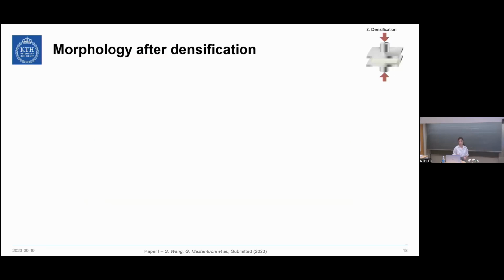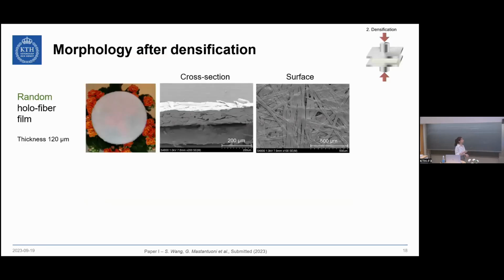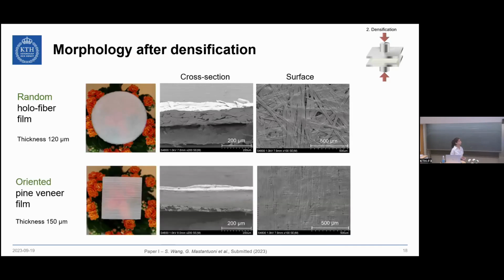What happens after densification? In the first case, with the random in-plane hollow fiber film, we can see random in-plane fibers from the surface, and from the cross-section we can see a lot of gaps inside the structure, which tells us that the packing is not very efficient. Instead, if we press the material that kept its original alignment, even if the material is slightly thicker, its packing is much more efficient and the structure is much denser. At the same time, we're also preserving the alignment of the fibers.